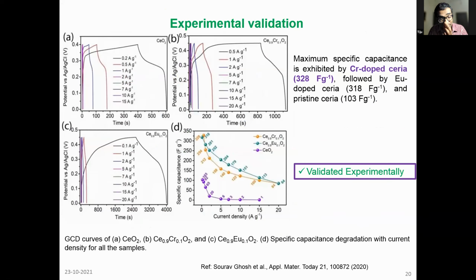So the experimental validation. As I said, we were trying to come up with a single predictor approach to coming up with the right dopants that would make ceria a better energy storage material. And here you find the results. Previously you saw that chromium enhances the oxygen vacancy concentration in ceria, and that would inevitably translate to a higher specific capacitance in measurements such as this one. You will find that this particular chronopotentiometry clearly indicates that chromium doped ceria is providing greater specific capacitance. This is the work of Sourav Ghosh, who is co-advised between Professor Rangarao and me. Next, please.